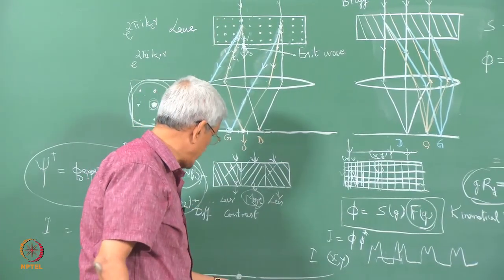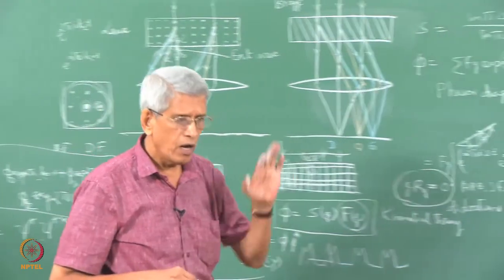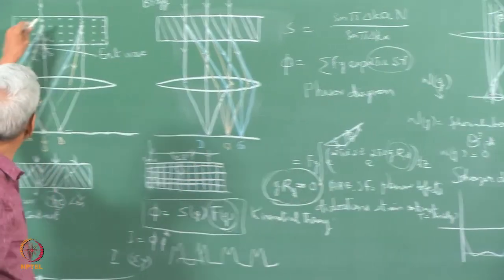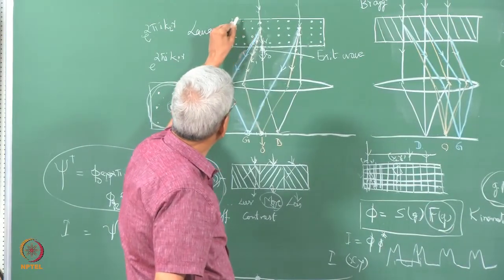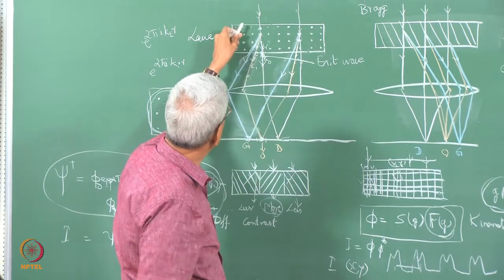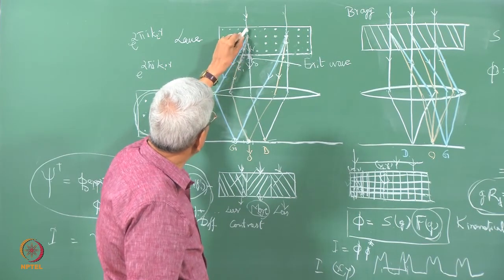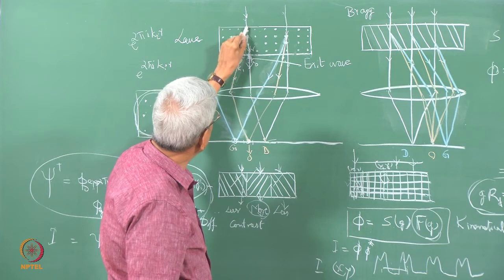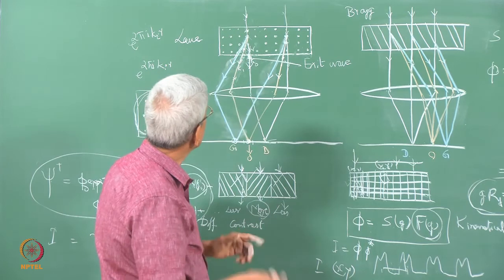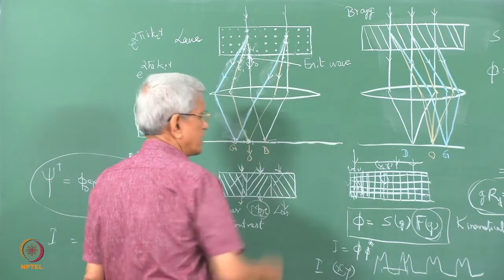For interpreting the high resolution image, what we essentially do is assume that as the electron beam enters the sample, a Coulomb interaction with the periodic potential of the sample takes place, and as the beam passes through the sample, we assume that the potential essentially adds a phase to the wave and no other change takes place. So the wave which comes out at the back will have its phase altered.